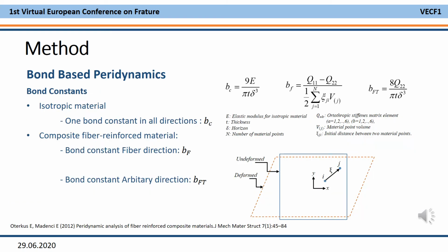Peridynamic bond constant. One bond constant for isotropic material is defined. Because an isotropic material is independent of directions, the isotropic bond constant depends on elastic modulus, horizon, and thickness. Composite fiber reinforced materials are directionally dependent. Therefore, two bond constants are defined: one in fiber direction, the other in arbitrary direction.